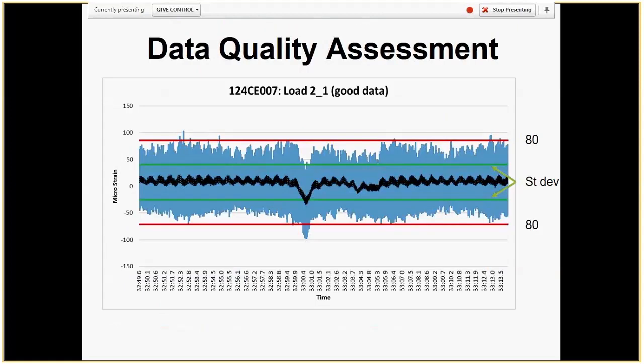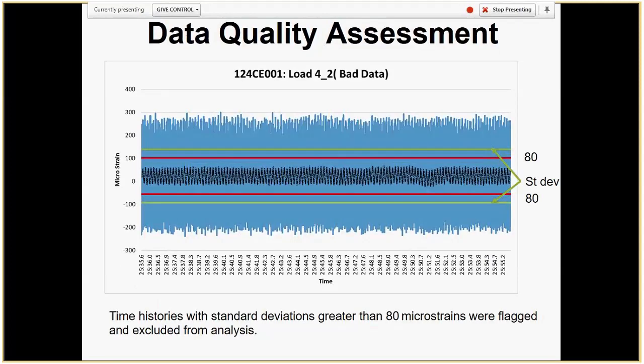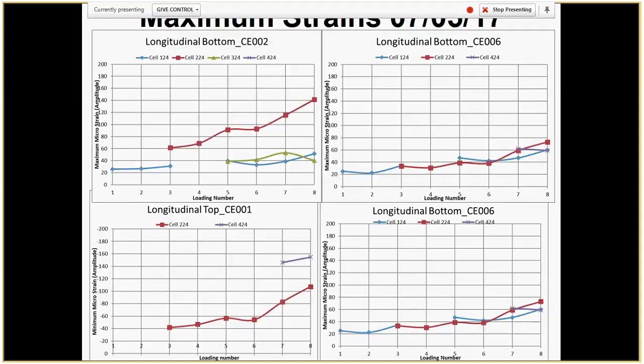Second, we reviewed the data and variability in data and found that if the standard deviation is more than 80 microstrain, then most likely the data are not reliable. So in this case, it's an example of pretty good data. The standard deviation is much lower than 80, and in this case, you can see pretty bad data. So they're not quite reliable, and we decided not to use this data. And this slide shows that after we eliminated all the questionable data, we have quite consistent trends from section to section, from cell to cell.